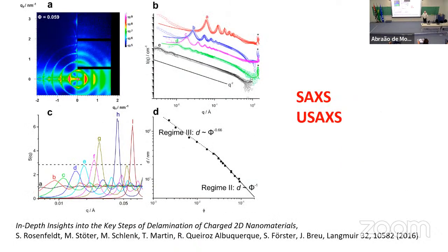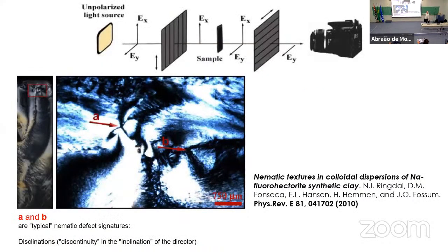Also, eventually, in the last, let's say, 15 years, many people have studied this quite a bit. And this is a typical problem for small angle X-ray scattering. So you get peaks from the orientation of the platelets. And in some places, you actually get fixed distances. So it's not really nematic, it's more like a smectic, because you have a characteristic distance between the platelets. So you see peaks in the small angle scattering when you shoot X-rays on such a suspension. This kind of nematic organization of suspensions of clays, you can also observe in cross polarizers. And you see the typical birefringent textures and defects.